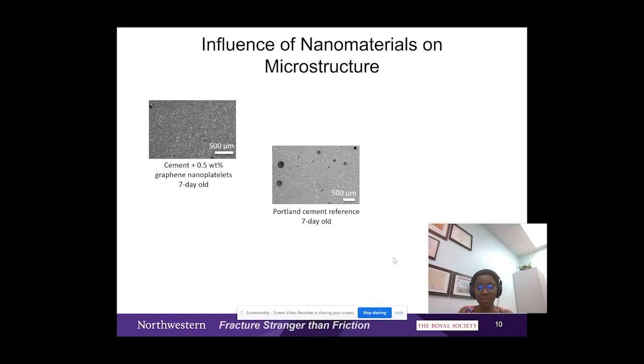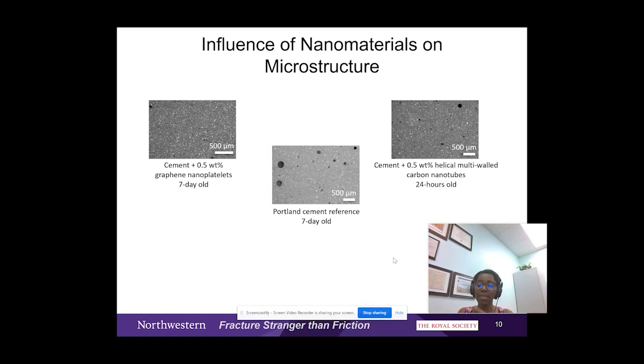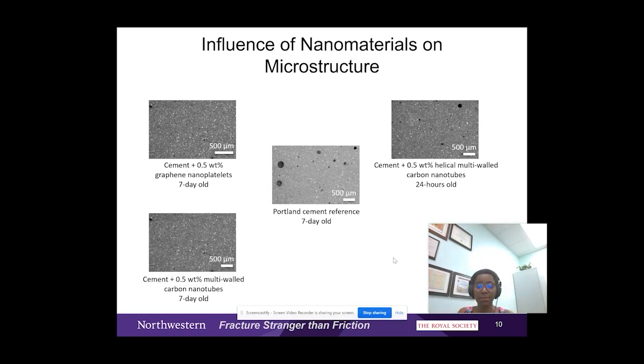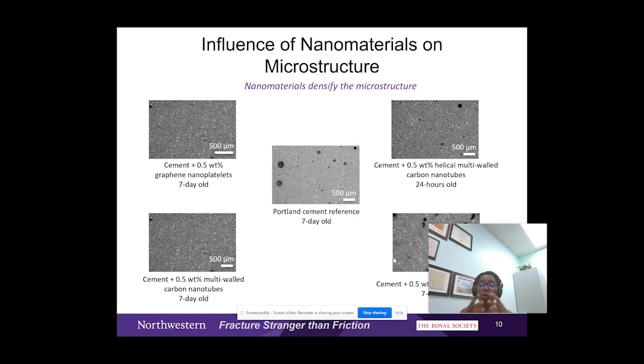The first question I ask is, how do nanomaterials influence the microstructure when we have graphene nanoplatelet cement, for instance, when we have helical multiwall carbon nanotube reinforcing cement, multiwall carbon nanotube, or in this case, carbon nanofibers? And overall, what I observed is that there was a reduction in the microporosity, both in the quantity and in the size of the pores, meaning that nanomaterials tend to densify the microstructure of cement matrices.